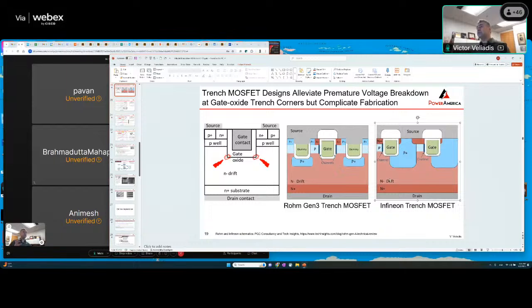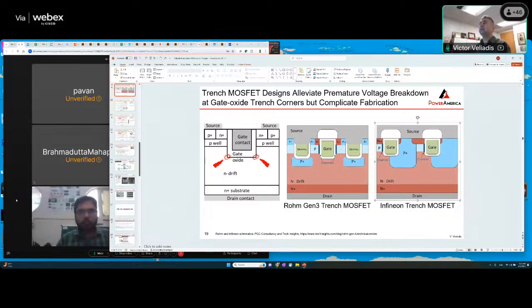So there's no clear win for the trench MOSFET in the low voltage area. Wolfspeed and ST are doing planar, ROHM and Infineon are doing the trench, and the performance is comparable. Otherwise, the market would have shifted into the trench if the trench was a superior device. So both are viable. But again, once you exceed 1.7 kV, the trench doesn't really help you. You're reducing channel resistance, but it's negligible compared to the thick drift layer resistance. So it doesn't really help you in that case.